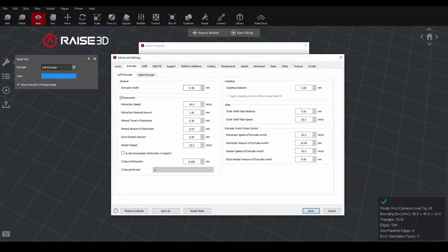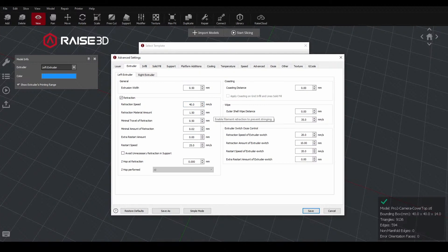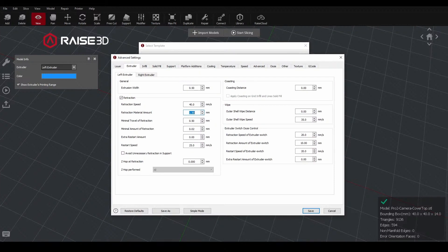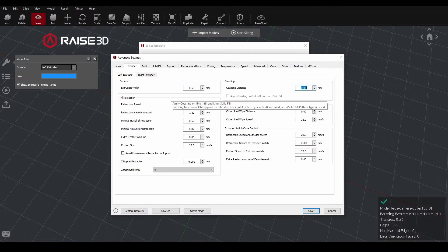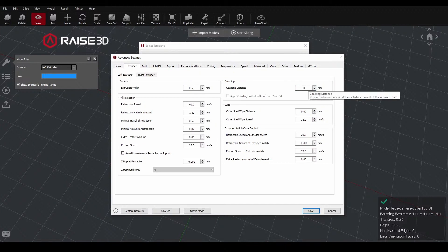Under our extruder tab, we have the options to adjust the retraction speed and the material amount. I've had pretty good results with our new TPU increasing the retraction speed a little bit and the retraction material up to two millimeters. I wouldn't really go higher than that. But that just allows it to basically pull that extra material back up out of the hot end so it's not directly at the end of the nozzle and it's less likely to leak as aggressively with that increased retraction. Working in something else like the coasting distance, this can help with other parts as well if you're seeing beading at end points. But essentially this is going to stop the extruder from continually pushing out material as it gets close to the very last section of any layer path and just let the residual pressure finish that off. And that should reduce the stringing as it transitions to something else. So I'll typically set that to a point two or I can increase it as needed. But if I keep increasing it, then I'm running the risk of it stopping the extrusion too soon and that can lead to gaps in the layer since it's not extruding all the way to the end of the paths.